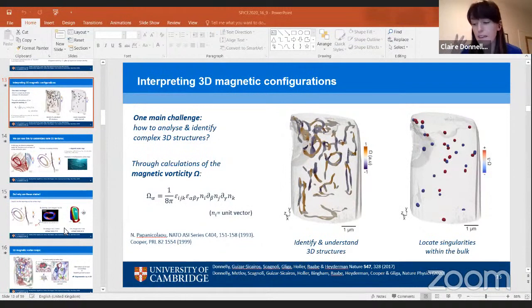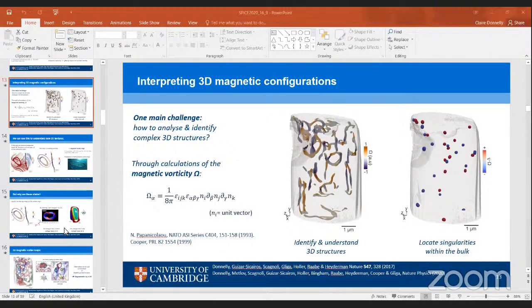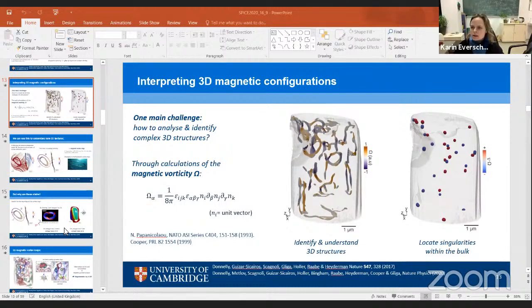However, what we think might be going on is that there might be some relation. We observed that the vortex rings often occur in the vicinity of block points, and it's likely that block points may be pinned themselves. So it may be a kind of indirect pinning, but we're still looking into this in more detail to try and understand exactly what's going on. Okay, thank you.